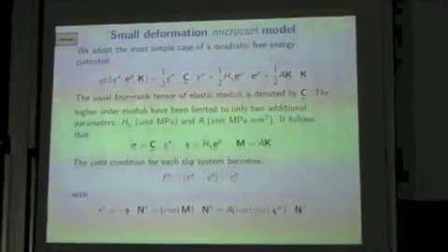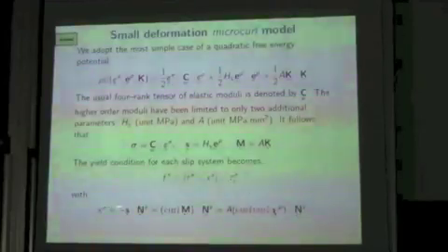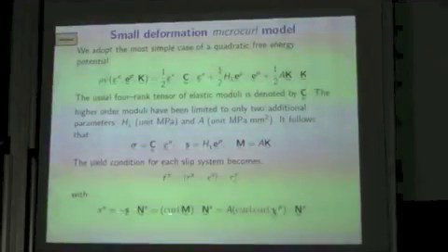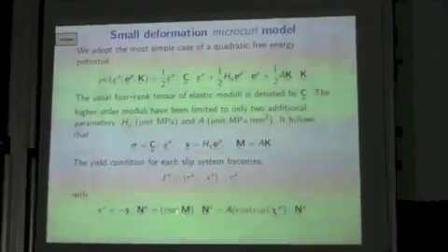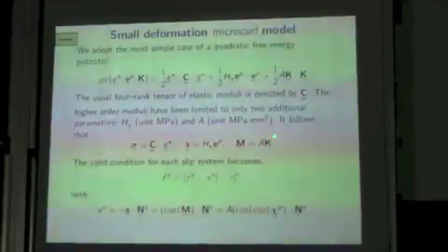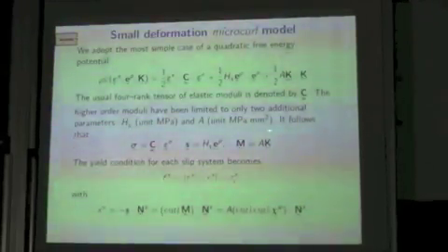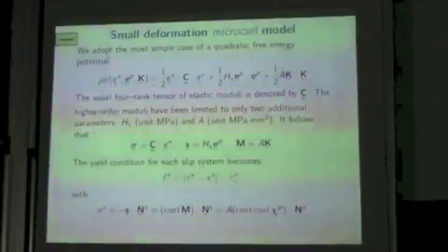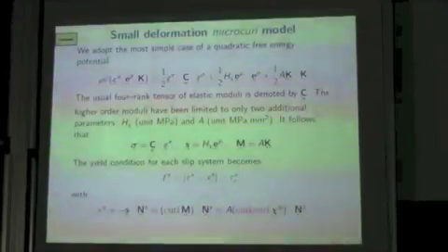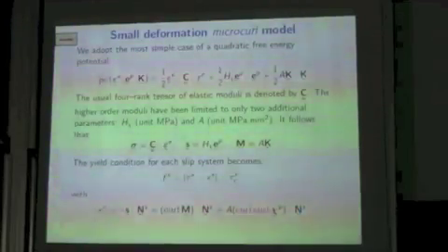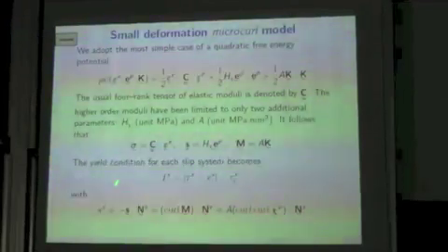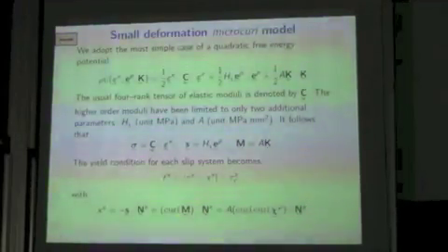And now look at the Schmid law, the generalized Schmid law. Remember, X was related to the relative stress, which is nothing but the curl of the double stress, but the double stress is proportional to the curl of the micro deformation. So you have simply that X is the curl of the micro deformation. And this is how the second derivative of the plastic micro deformation comes into play in the yield function that you have here.